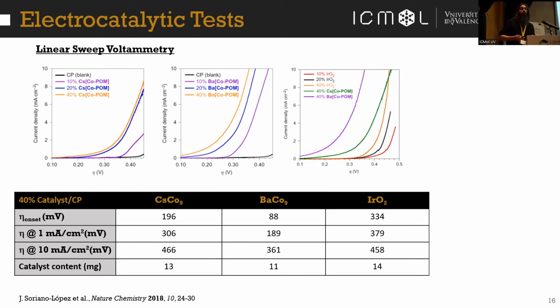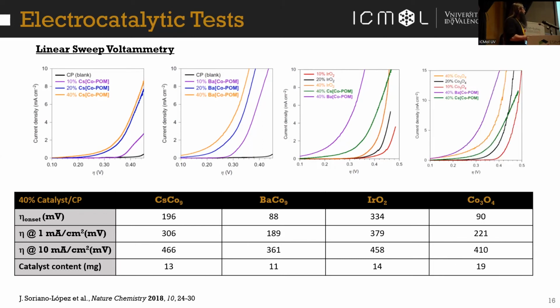So we also compared it with cobalt oxide. And we can see here that cobalt oxide was also quite active, but it couldn't match the activity of the cobalt-9. And just so you know, 40% of cobalt oxide possesses many more atoms of cobalt than 40% of cobalt-9. So we would need a huge amount of cobalt-9 to be converted into cobalt oxide to have this activity. But I will show you more proof that we are not forming cobalt oxide under these conditions.